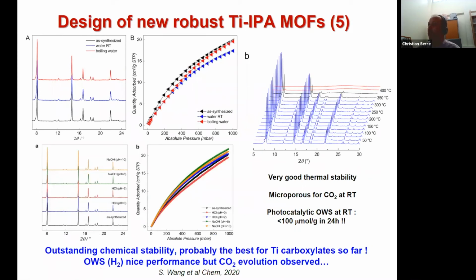We are also interested to test the stability of this material, and it was surprisingly stable, even more stable than our best MOF reported so far. Even in boiling water, we did not see a change of porosity, a change in particle size and shape or anything. And it was also more stable under basic condition than, for instance, MIL-125 and so on. As expected, the thermal stability was relatively good, because chain-based materials are relatively more stable than cluster-based materials. And it was stable up to more than 300 degrees C.